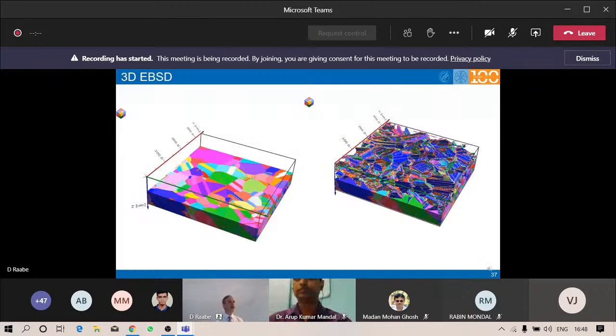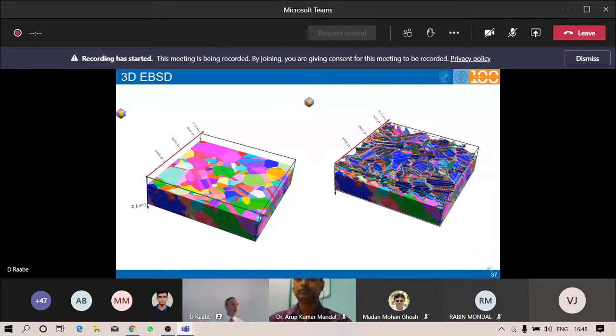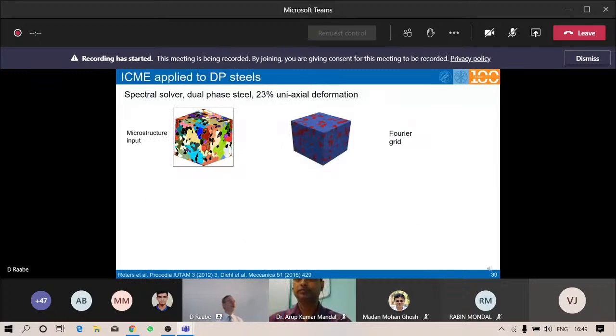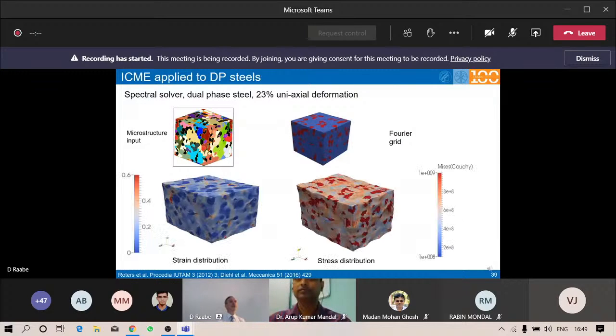Now we do the same thing also here for steels. I've shown that movie already before, where you get such 3D data, for instance, now again for a dual phase steel. And here we ran such a box of 3D data by DAMASK, and you see you get a real high fidelity simulation of the strain and stress distribution also from such 3D microstructures.